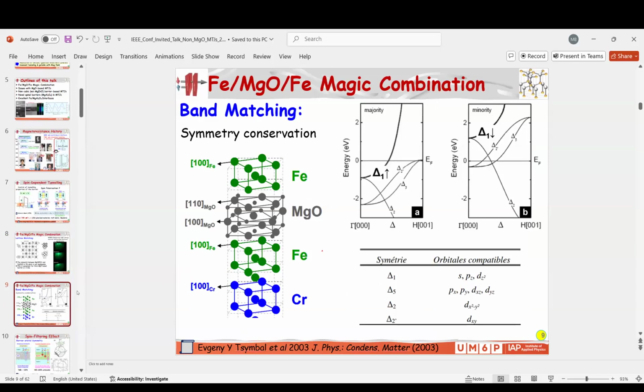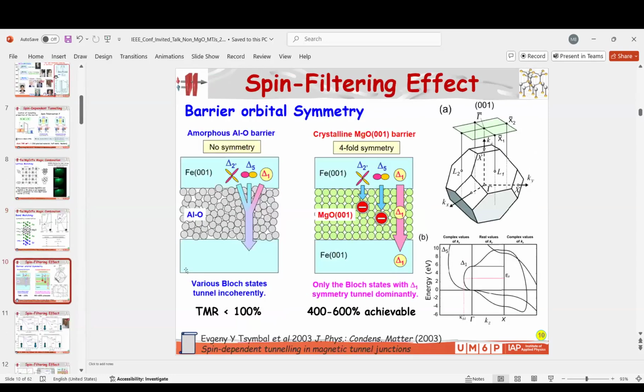So without trying hard to find the Heusler or half metals, which are very complicated materials, the iron itself behaves like half metals. At the Fermi level, we have the bands of up spin, but the minority spin are absent around the Fermi level. So when we go to the parallel one, we have delta 1 up, anti-parallel, the delta 1 down, minority are absent. This is one good thing.